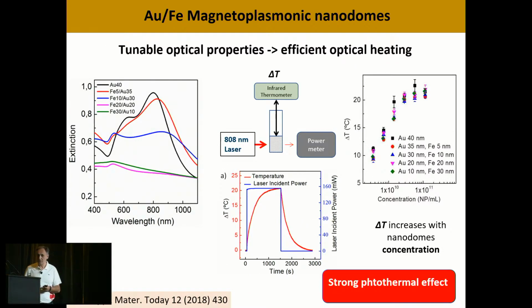Here I show you the optical properties of the nanoparticles. Here I show you the absorption. Well, actually, this is the extinction, which is the absorption plus the scattering. And we see that when we change the ratio of gold and iron, the extinction shifts to higher wavelengths and the intensity decreases.